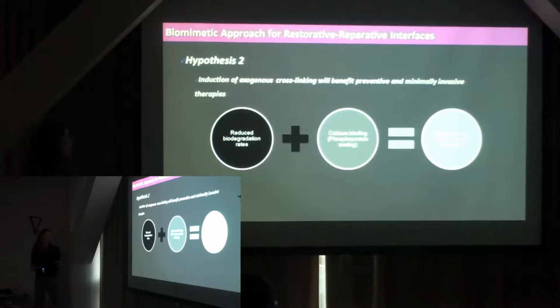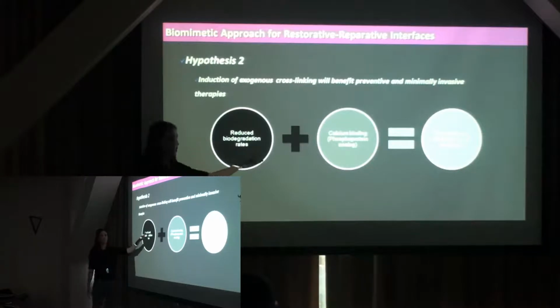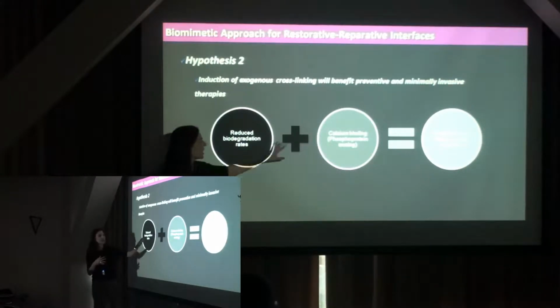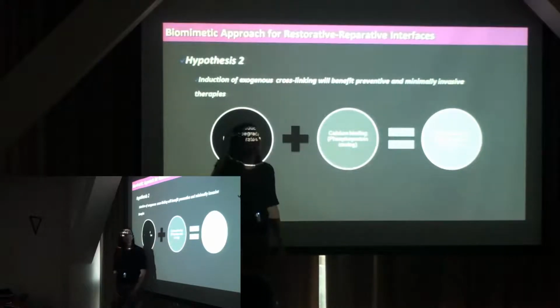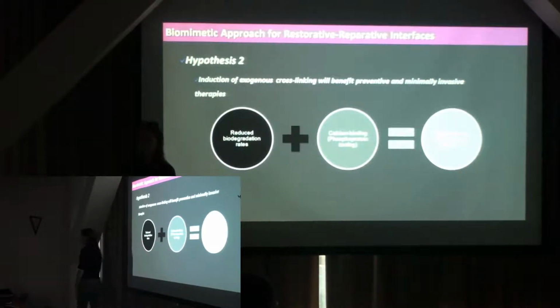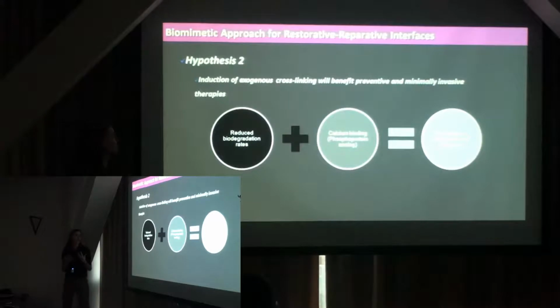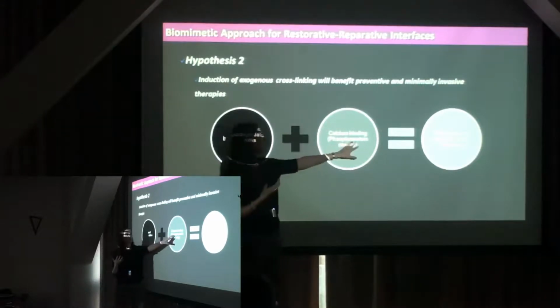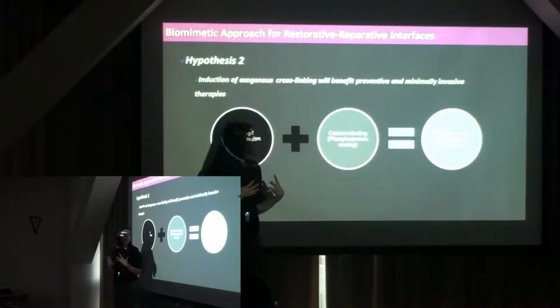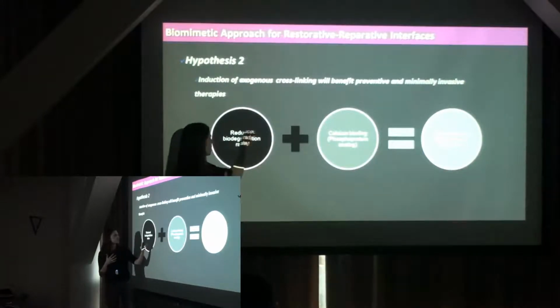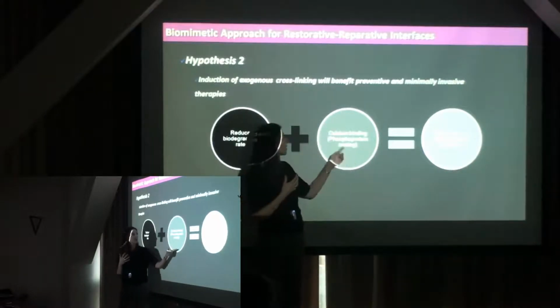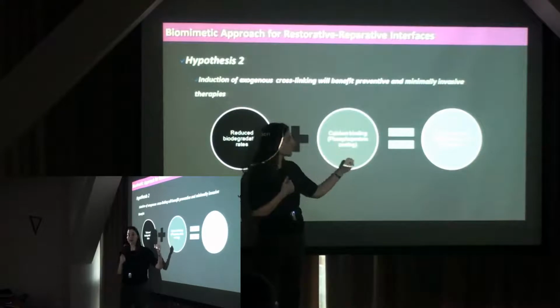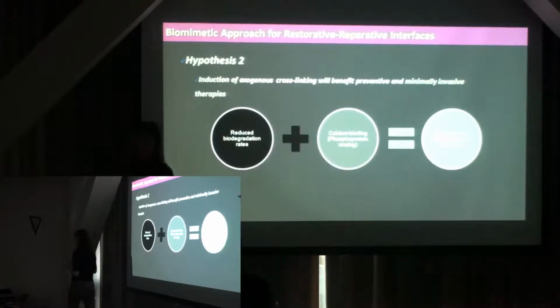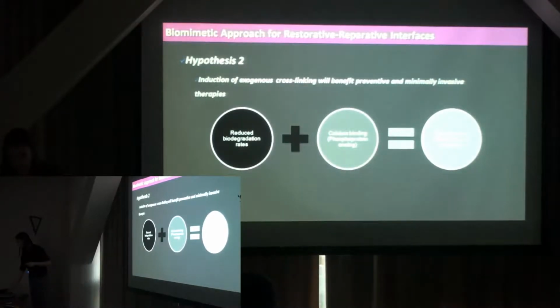So how can we do that? We basically reduce the biodegradation rate. So the collagen is the backbone for mineralization, right? These proanthocyanidins are also calcium binding, so they can work as a phosphoprotein analog. The phosphoproteins are in charge of this mineralization process. So if we can slow down degradation and have it there to help attract calcium, maybe we can develop a new strategy to remineralize teeth.